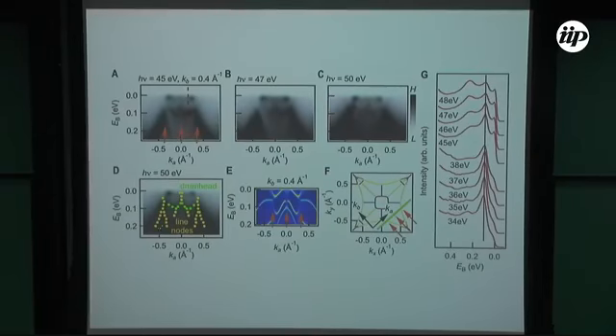So then we can isolate the bulk band structure and the surface band structure by probing their kz dependence. If something is not kz dependent, then it's surface. And if something disperses in energy in kz, then I know it's three-dimensional, right? I can probe that. Based on that, we identify the signal here is coming from the surface. Here we show that kz dependence, that as I change kz, that signal doesn't. So this signal corresponds to this thing.